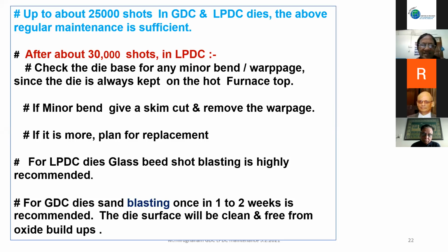In the low pressure die casting dies, check the die base warping always on the furnace. It is on the hot bed, so it is likely to warp. Even a very mild warp will leave a gap between the furnace and the die. The metal will not get injected with full pressure. After all, you are applying a pressure of maximum 0.4 or 0.3 kg per cm square on the furnace. If there is a loss of pressure, metal won't rise. So you must be very careful in that one. It is likely to warp, so every 30,000 casts, you must take it and check. You can give a very fine grading also, say 0.1, 0.2, and see that there's no gap.